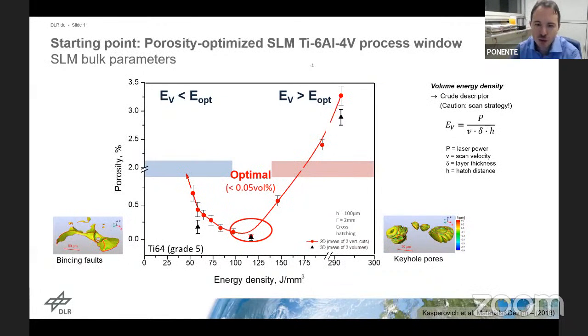What you find a lot in the literature, and what we also found, is if you then draw diagrams that at the bottom have an axis that shows the process parameters, either laser power or scan velocity, or a convoluted parameter like the energy density, you get these kinds of trends where you have an optimum in the middle, and at too low energies or too high energy densities, the porosity starts to kick in, either binding faults or balling, or on the other hand, the keyhole pores. So you have generally a process window in the middle that you accept in terms of porosity. Below 0.1% or 0.05% is acceptable for the process in our case.